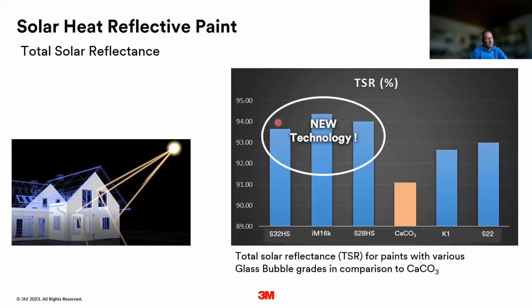And now you may ask the question, is this significant, an increase from 91% to 94%? Doesn't sound like a lot. And yes, it is significant, because you have to imagine that we have irradiation of 100% from the sun. In case of the standard paint, 91% is reflected and the remaining 9% is absorbed and transferred into heat. Here, if we have a reflectivity of 94%, only 6% are absorbed and transferred into heat. So that means that's one third better.